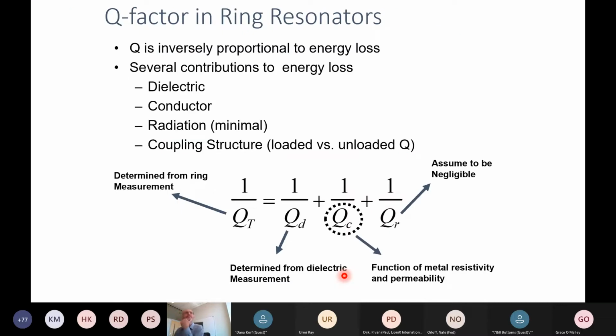So just going back, recall that when I talked about the attenuation, or alpha, there were the contributions of the metal, the radiation losses, and the dielectric. The same thing is shown here, but instead of alpha we have Q, and we have the same contributions: the dielectric, the conductor, and the radiative losses. So what we can do with that ring resonator is certainly measure the total Q of that resonator experimentally. And independently, we can also measure the dielectric fairly easily. I'll show that in the next slide.